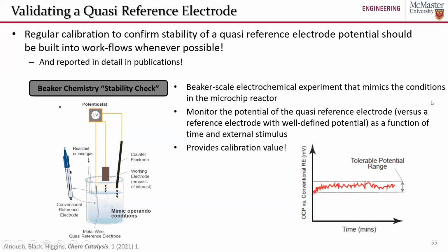So I have a question in the chat. Will the size of the reference electrode material affect the potential, since it depends merely on the redox reaction? So in principle, the size of the reference electrode should not dramatically impact the potential, because it's dictated simply by the redox processes or the redox couple that's formed on the surface.